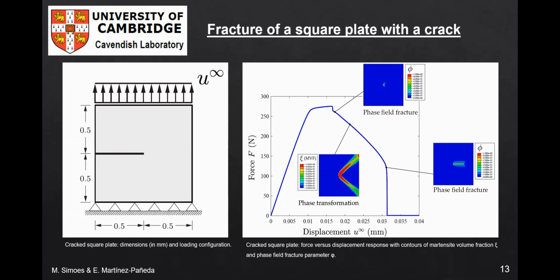Here, failure of a cracked square plate subjected to tension is analyzed. The results obtained are shown at the right in terms of the force versus displacement response, with the contours of martensite volume fraction and the phase field fracture parameter, phi, at different stages embedded in the figure. Differences from the response commonly observed in this classic benchmark are notable.